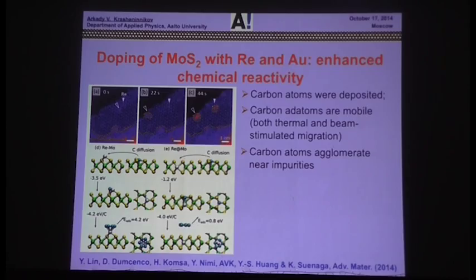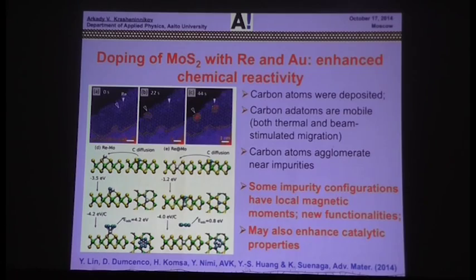Impurities are quite reactive, it's well known, and this is exactly what happens when you have a rhenium impurity in molybdenum disulfide. The formation of new nanocarbon, small carbon clusters, is stimulated by impurities in molybdenum disulfide. Again, this carbon is coming actually from hydrocarbon molecules present in the TEM chamber. So, to this end, doped molybdenum disulfide can be used for catalysis.